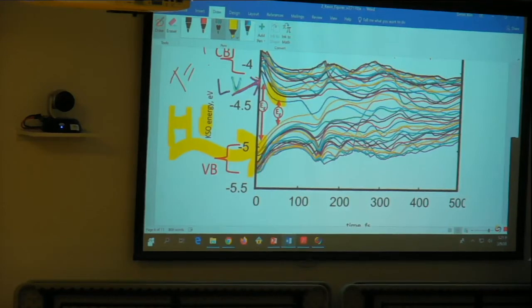It's due to non-adiabatic dynamics. In non-adiabatic dynamics, the nucleus vibrates. When the nucleus vibrates, the corresponding orbital positions change. So as time goes by, it's natural that the band gap between the HOMO and LUMO is going to change. When you take into account the nuclear vibrations and the temperature fluctuations, from my understanding, those two things are the main factors in reducing the band gap.